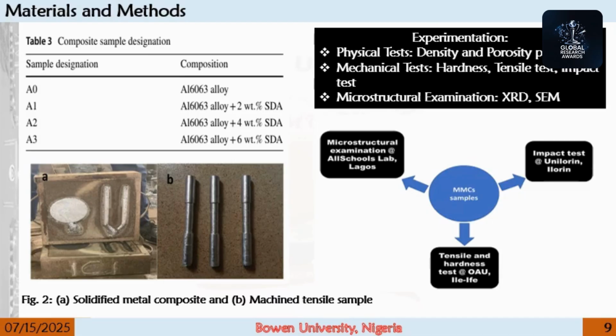The experiments carried out on these were to determine the density and porosity percentage. Density was determined using Archimedes' principle, and porosity was also taken. For the porosity percentage to be determined, the theoretical density was obtained and the experimental density was also obtained, and the difference between the two was used to calculate the percentage porosity. We also determined the hardness, tensile, and impact tests following the appropriate ASTM standard. And lastly, the microstructural examination was carried out for the sample after production and for the fractured surface of the sample.